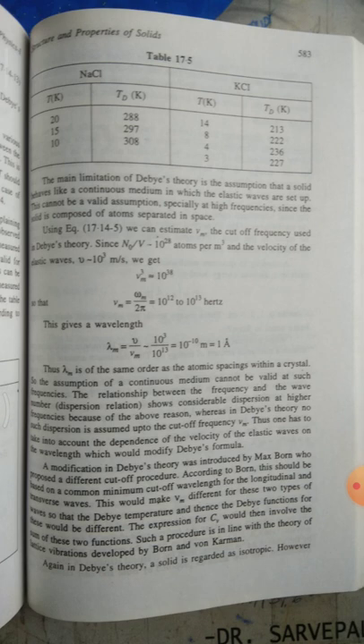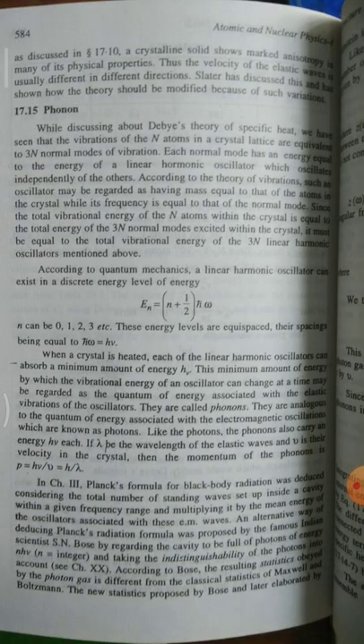Again, in Debye theory, a solid is regarded as isotropic. However, in a crystalline solid, anisotropy is shown by many of its physical properties. Thus, the velocity of the elastic wave is usually different in different directions. Slater has discussed this and has shown how the theory should be modified because of such variations. Okay, next I talk about phonons.